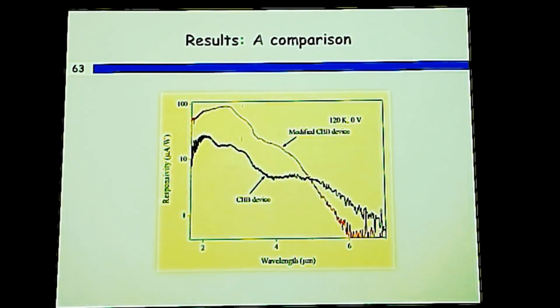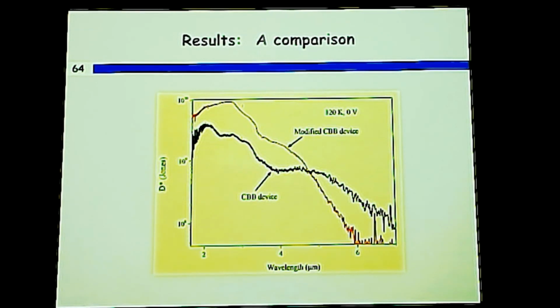So by comparison, original device and the modified device at 120 K, since there is no significant reduction in the photoresponse, the modified device shows higher photoresponse, and the original device with the blocking barrier shows weaker. And the difference in the range of spectra is because of the increase in the aluminum fraction in the modified device. With increase in the aluminum fraction, the energy barrier is now slightly higher, so the response threshold is slightly shorter. D star is also slightly higher in the modified device at 120 K.